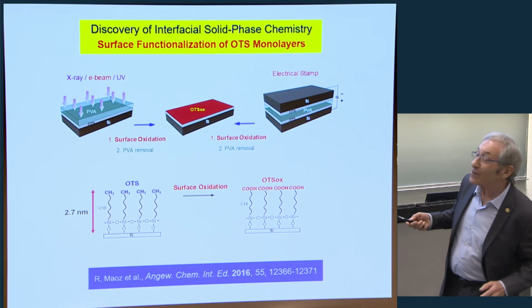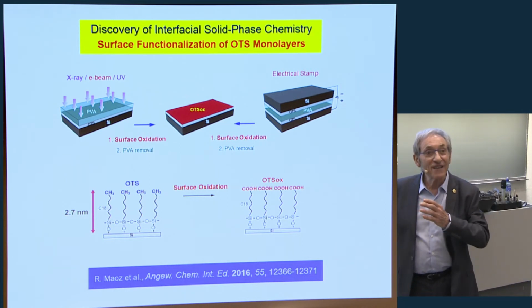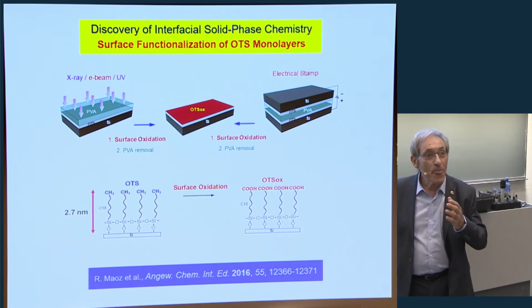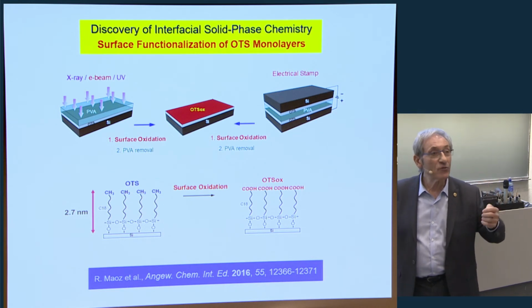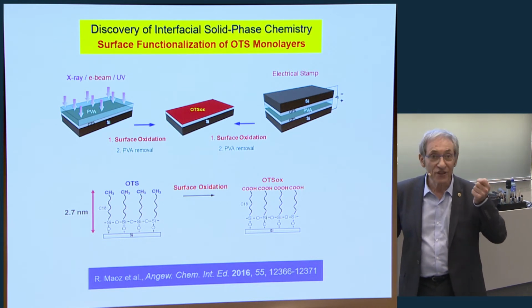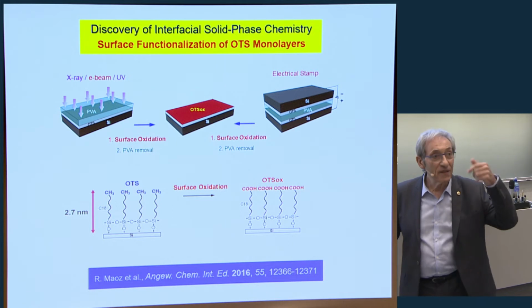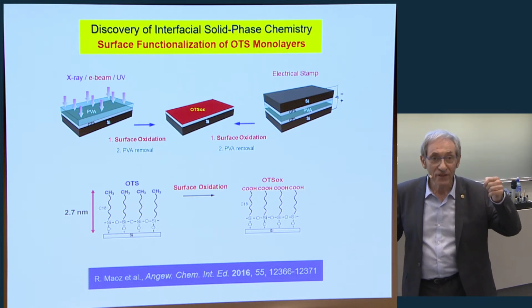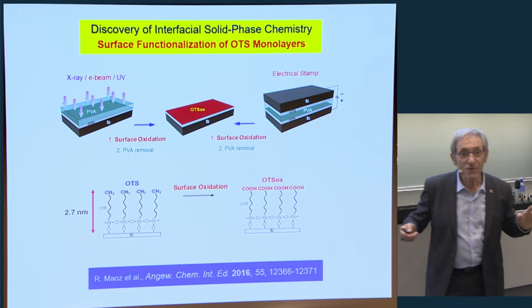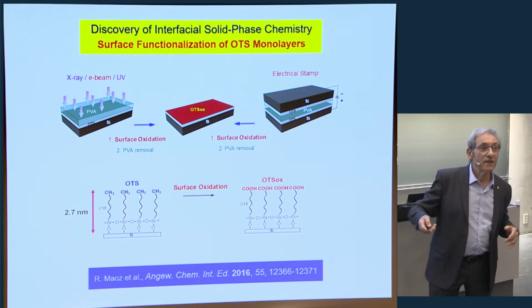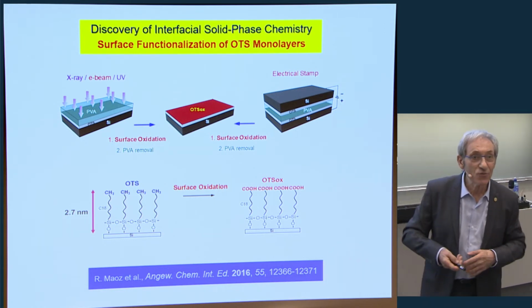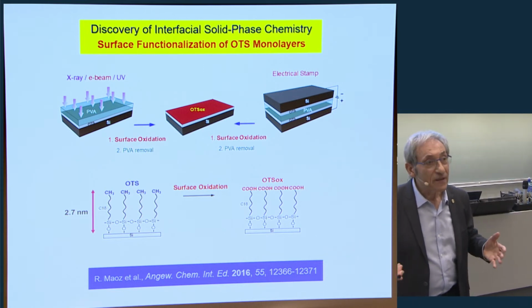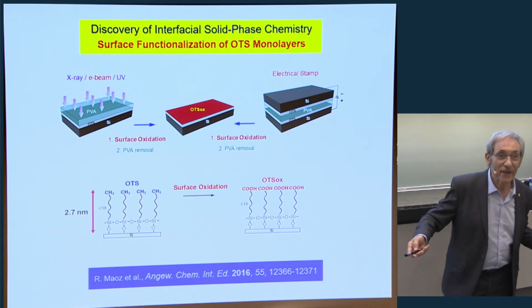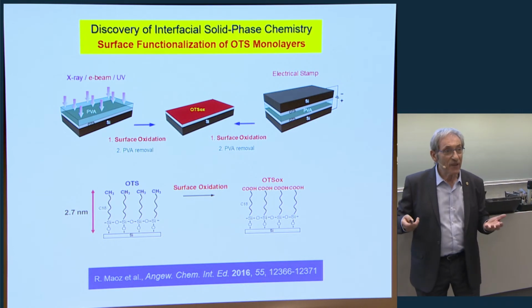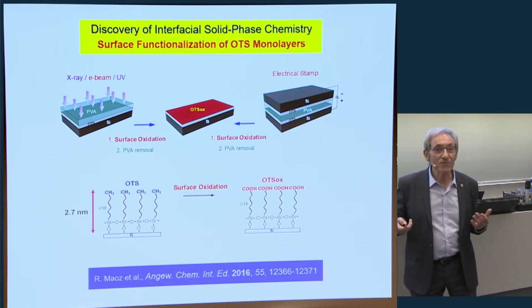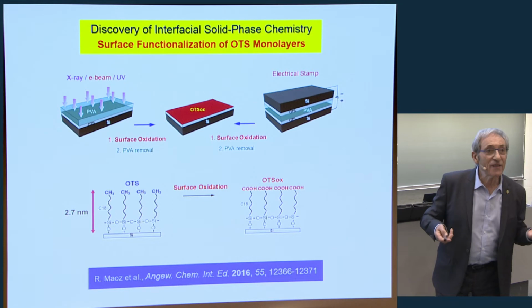So what I've shown was done with patterning with an AFM tip or with a stamp, for which we need water. You remember the droplet that condenses on the tip. Now this makes problems because if you want to move fast and you apply a bias, sometimes this water evaporates and then there is a break in the line that you want to make. So it is unstable.